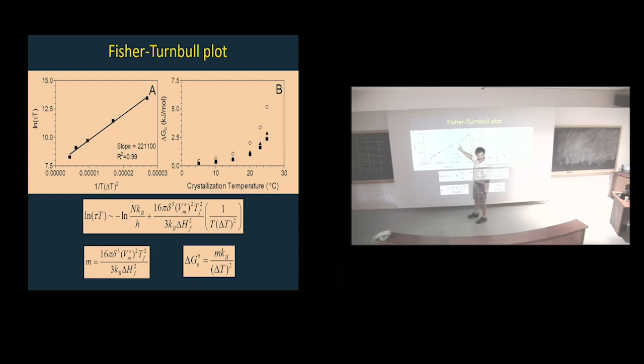And you get the slope, and that slope is called M. And M is all of this nightmare. And now, if you believe me, all you need to do is M times Boltzmann constant divided by delta T squared, and you have the free energy of nucleation. You can look at it and go, oh yeah, whatever, grade 10 arithmetic. And then you have also the slope term, which again looks scary, but it has just a density, a temperature of melting, an enthalpy of melting, and Boltzmann constant.